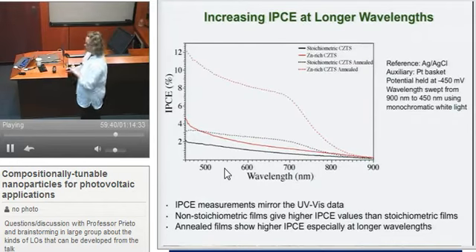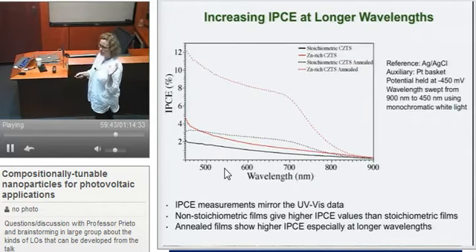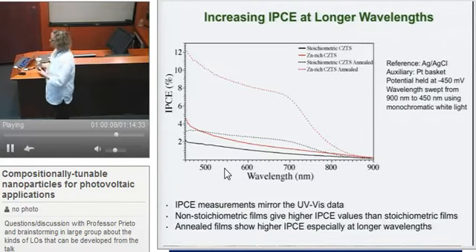Now, when we then take that data and calculate how many photons are hitting the sample, that's the incident photon part of this, and then the current efficiency. What's important here is that the copper deficient sample that was heated is much more efficient over a much broader wavelength range. And we don't actually know why that is anymore. Again, we looked at these particles really carefully to study the composition and the structure, and it turns out to be a much messier picture than the parts we measured before. But what we do know is that we can target a stoichiometry and get better properties. And I think that's kind of the important first step in here.